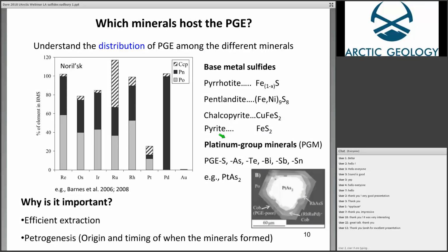It's really the precision, because you have errors in determining your tracer elements by laser. You have errors in determining your PGEs by whole rock analysis. That's pretty precise. It's really the laser, I would say, for elements, in particular in chalcopyrite. There are interferences, as I mentioned, on ruthenium, rhodium, and palladium that you need to take into account. That might give some error in accurately determining the trace elements in your sulfides.